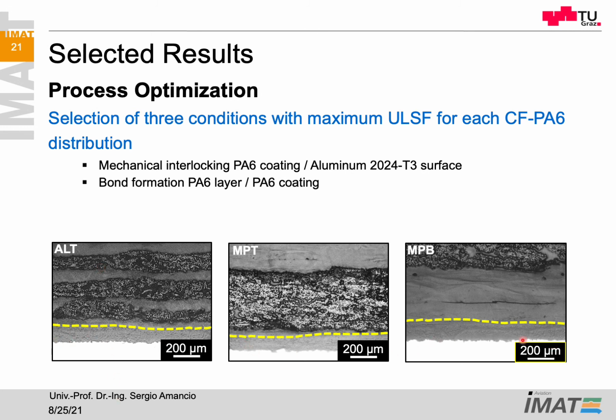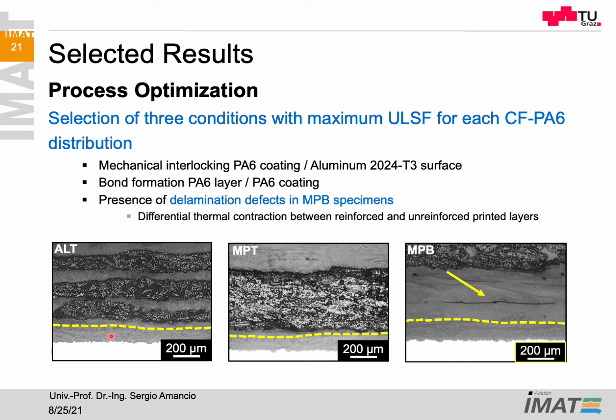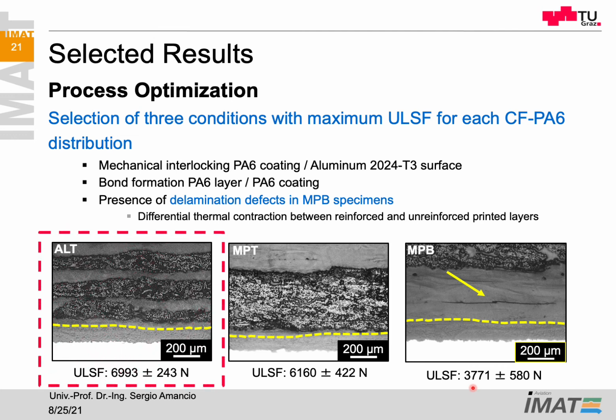As you can see, there are no visual gaps between the metal and the polymer in the coating layer, and there was a very good bond formation between the first unreinforced layer and the coating. But in the case of the mid-plane bottom, we saw some delamination defects within the first unreinforced layer, as you can see here. This is still under investigation, but we believe that this is due to the differential thermal contraction between the unreinforced volume and the reinforced volume in the printed layers, which generates those residual stresses that led to the delamination cracks. So this explains the reduction of mechanical resistance.